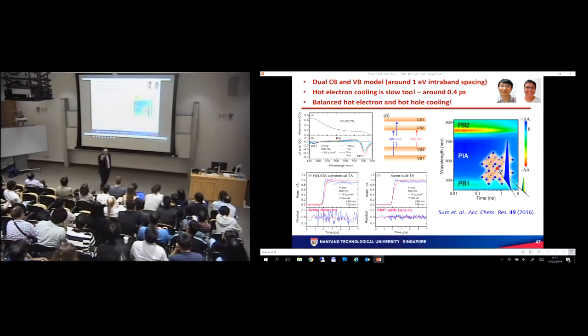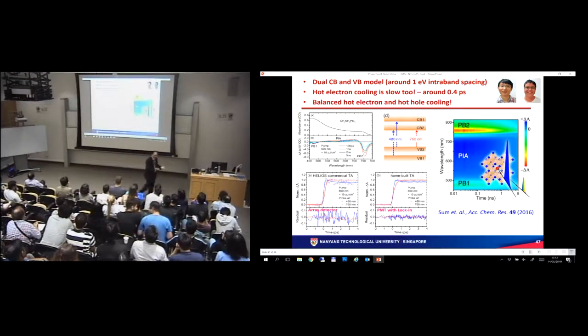Immediately it changes the whole game, because having only the hole that is slow is not going to help if your electron is not slow enough. And having an electron and hole that are not cooling at the same rate will give you a lot of problems. Again, the magical thing about the very small, similar effective mass of perovskite comes into play. So it came with a very nice coincidence here. Having balanced hot electron and hot hole cooling definitely makes it much more feasible. It looks more likely that you can actually attempt to make a device with this concept. So we have therefore stumbled upon a very interesting system that we can potentially use.